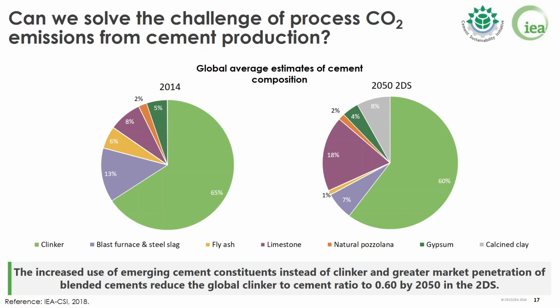Then we see that in 2050, the share of composition of cement will change in favor of more use of limestone. Limestone is already widely used today as a filler, but it will increase its percentage share. And there is also a new entry that is calcined clay. Calcined clay is already used today in a specific location where it is today economically viable, but is expected to be used more and more in combination with limestone in the future. Calcined clay is the result of drying, crushing, and calcination of raw clay. And so its applicability depends on local availability and treatment cost.